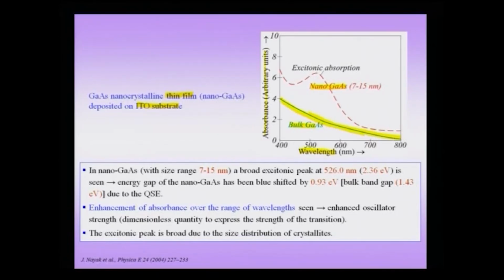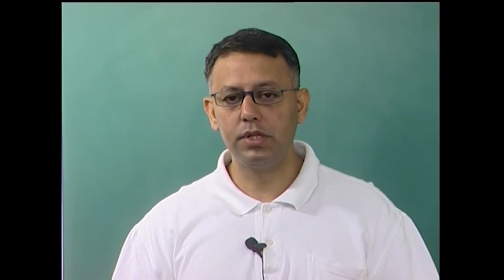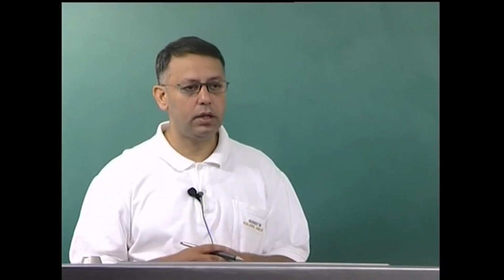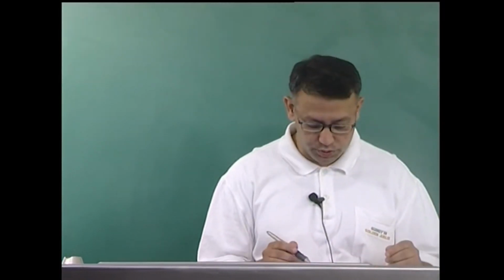So the wavelength is increasing in the right hand direction, the energy is actually increasing in the left hand direction. So, this is my energy. So, with increasing energy, you are seeing an increasing absorption. What is prominent in this absorption spectrum, of course, one of the things is that you do not find an excitonic absorption, because this is now a room temperature experiment, wherein you expect that the exciton has been dissociated.